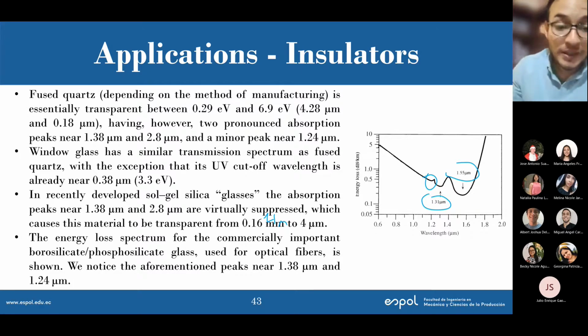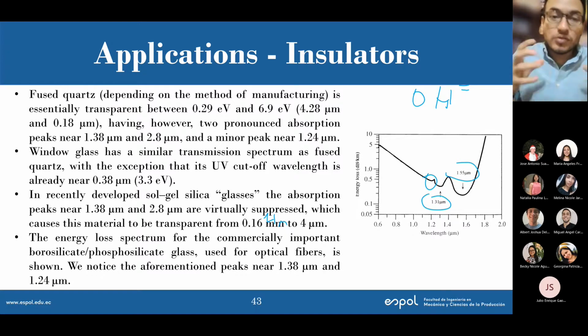So there are peaks for these materials, and they happen because of the vibrations between the hydroxyl ions, the OH ions. There will be some traces of these hydroxyl ions in this glass, and at those frequencies there will be stretching vibrations between these ions, and that's why you see these absorption peaks. Otherwise, you wouldn't have any of them.